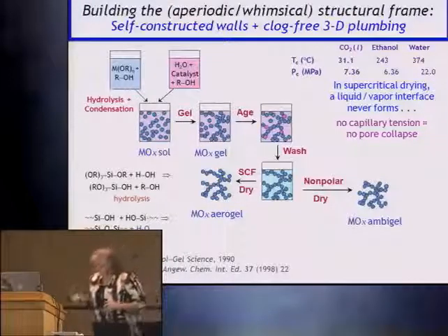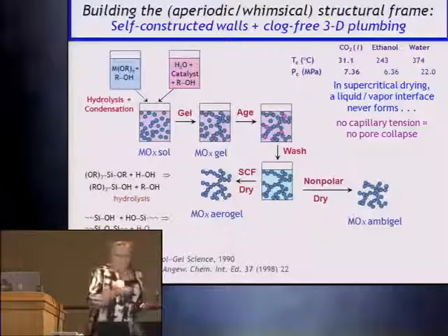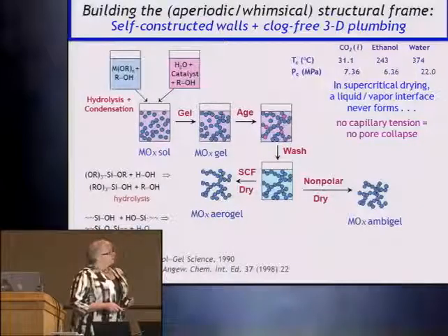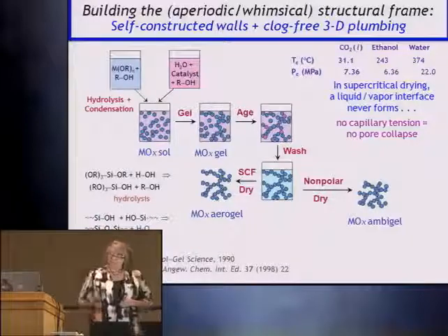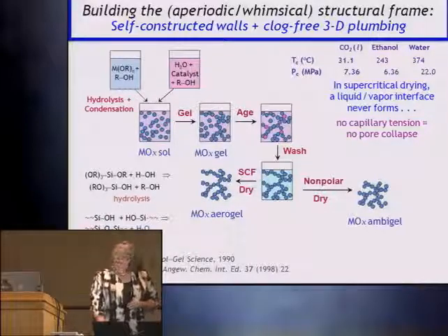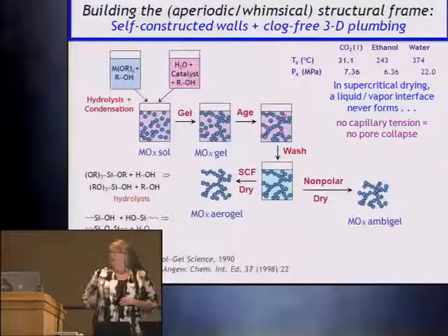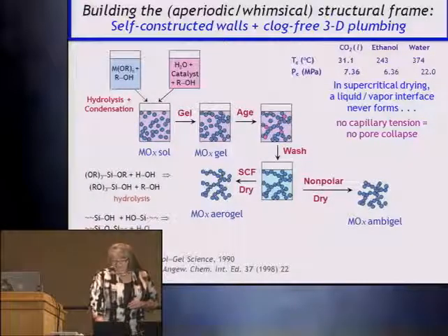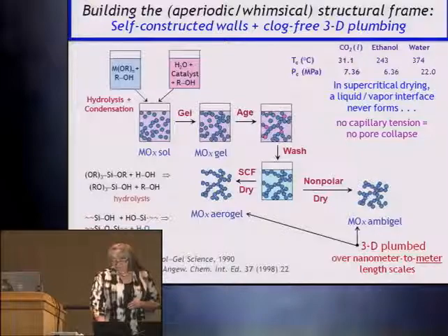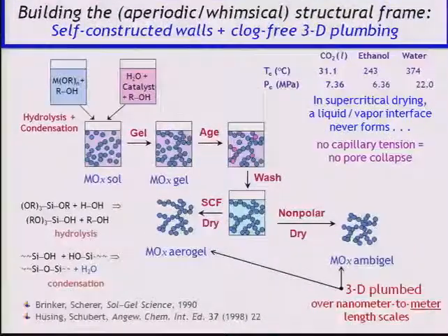The canonical cartoon for an aerogel are these nanometric bits of whatever your oxide or carbon species is, covalently bonded, filling a volume where most of the space is open on the order of tens of nanometers, or mesopores. Now, some people really would like to avoid having to pressurize a reaction vehicle, so you can also put a non-polar organic, low surface tension into the pore fluid and just dry that, raise the temperature a bit. Voila, you have an ambiently pressure-dried gel where you still have kept the porosity interconnected in 3D. We call those ambigels. The important point is, unlike most templated porous objects, this retains its structure from nanometers to meter length scales. It's very hard to take templated porosity and retain any registry much past 5 or 10 microns.